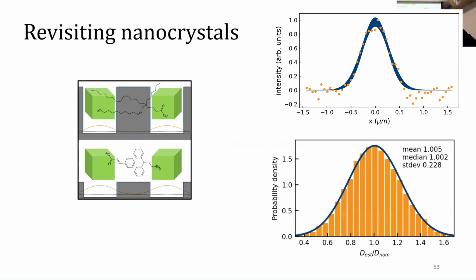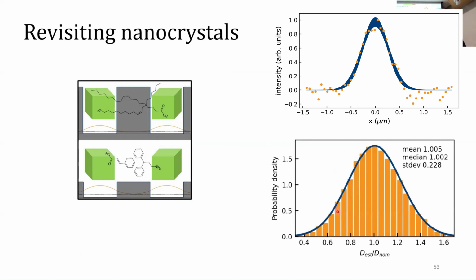So revisiting the nanocrystals, now that I've done this study, I went back to the nanocrystals and said, okay, how was my contrast to noise, and how precise are my fits? Here's one example where I did a Gaussian fit, and then I looked at the 95% confidence interval of that fit, and it looks kind of big, and that was what I was concerned about. But then when I do the fitting of the diffusion coefficient, I think I did 10,000 fits here. And as you can see, almost all of them are within 50% of the nominal value. If that was my level of tolerance for precision for that particular experiment, which looking back at those histograms, this is pretty good. And that was encouraging. Great to see that. And folks following me will do some more work in that respect.